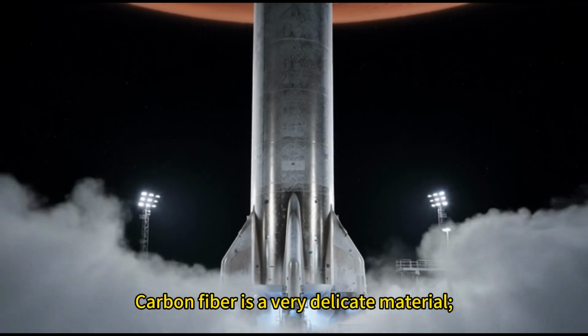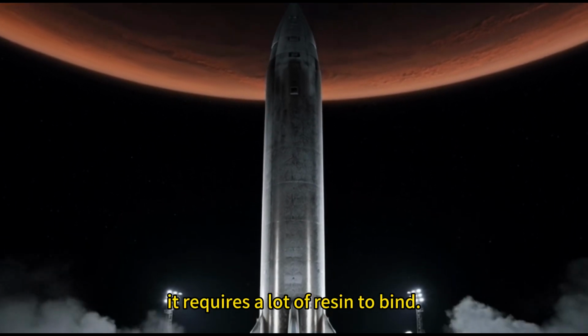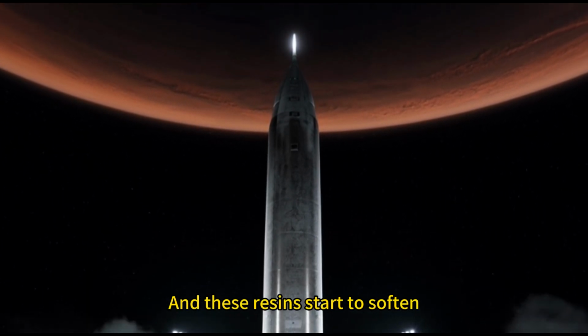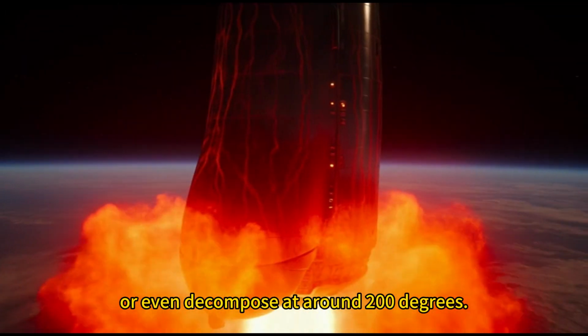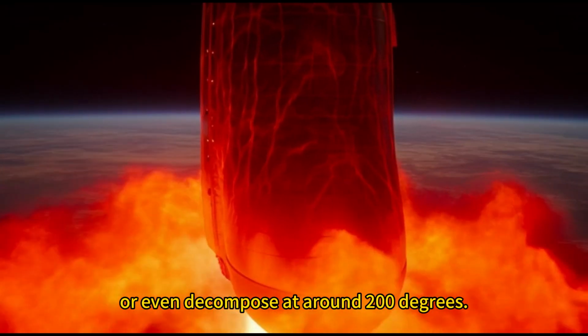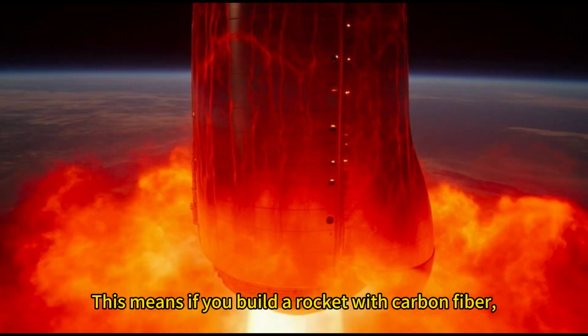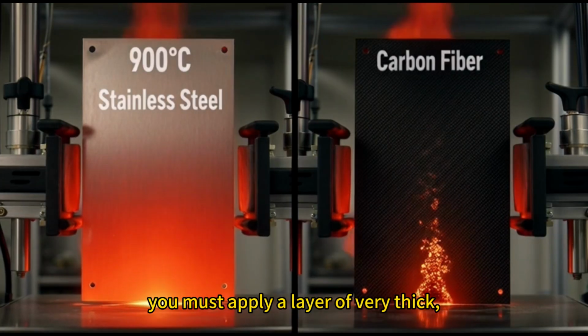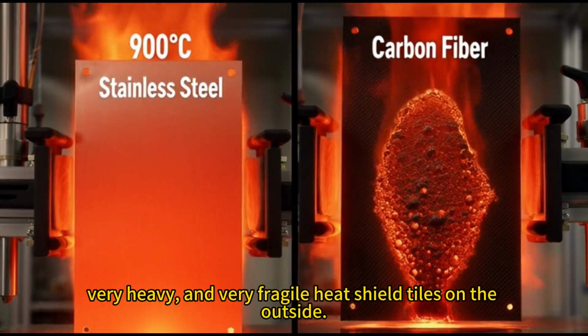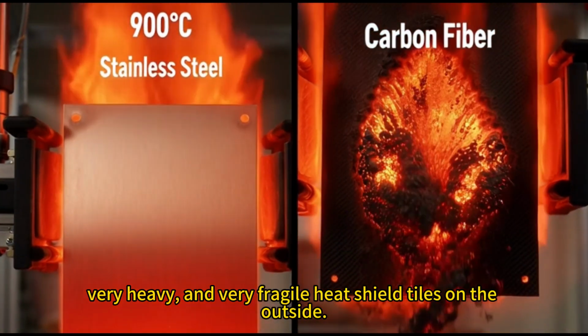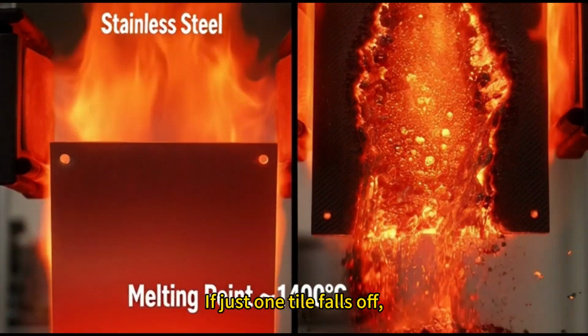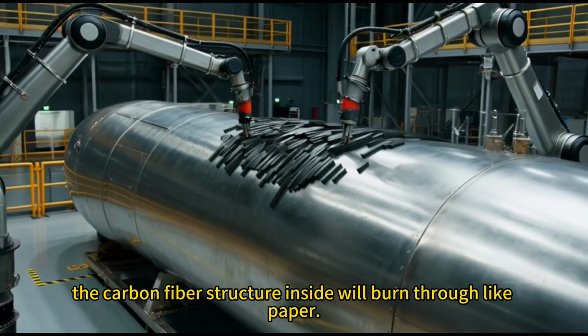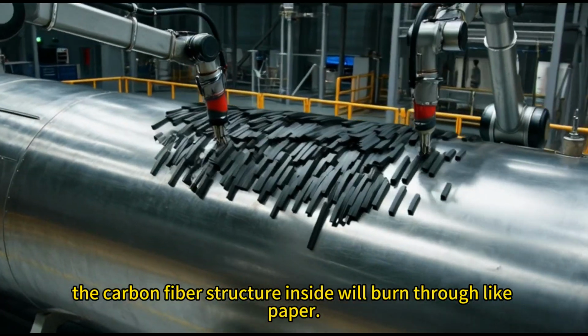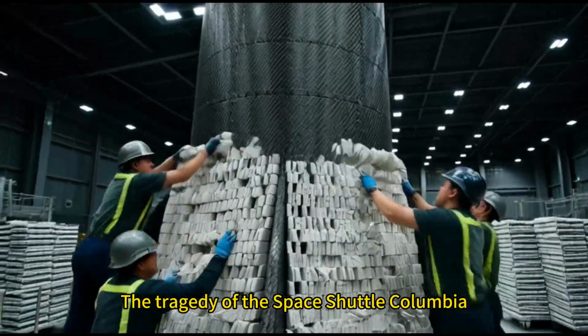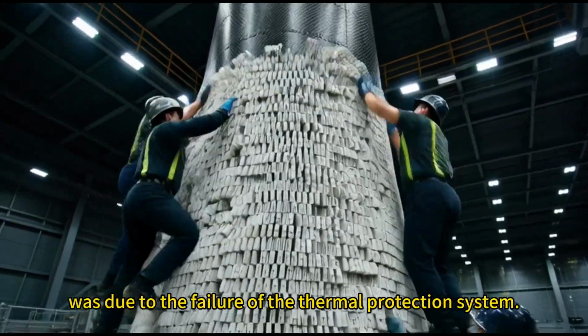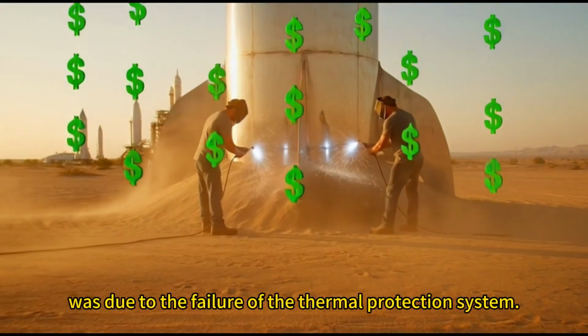Carbon fiber is a very delicate material. It requires a lot of resin to bind, and these resins start to soften or even decompose at around 200 degrees. This means if you build a rocket with carbon fiber, you must apply a layer of very thick, very heavy, and very fragile heat shield tiles on the outside. If just one tile falls off, the carbon fiber structure inside will burn through like paper. The tragedy of the space shuttle Columbia was due to the failure of the thermal protection system.